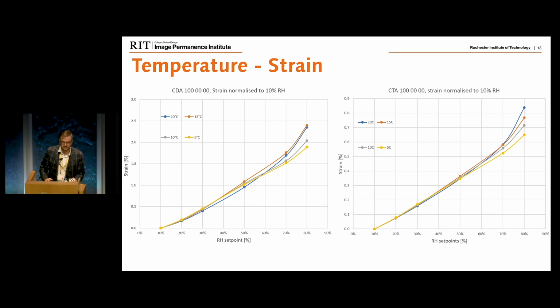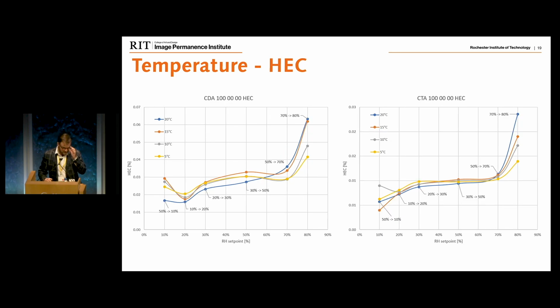And as you can see, there is almost no effect until you go to 70% RH and above. Those are normalized to the dry state, right? That's why we're starting at 0. In diacetate, this is a little bit more wild, but still fairly flat and stable. So it shows that the temperature has rather little effect on this, and the same obviously shows in the humidity expansion coefficient calculations, that what you're getting is very little fluctuation when you're comparing one temperature from another between 5 and 20 degrees Celsius.